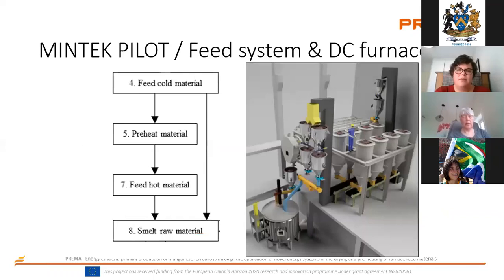For the DC furnace, we will want to feed either cold material directly into the furnace or the material via the preheater to the furnace itself. On the right-hand side of this sketch, you see the feed system. We have 4 bunkers that can feed the rotary kiln to the back. You see the bucket elevator there feeding into the rotary kiln to preheat materials. There are also 4 bunkers that can feed into the bucket elevators, feeding then cold feed into the furnace. We will be able to run that simultaneously. And what you also notice on this slide is the DC furnace has one electrode.